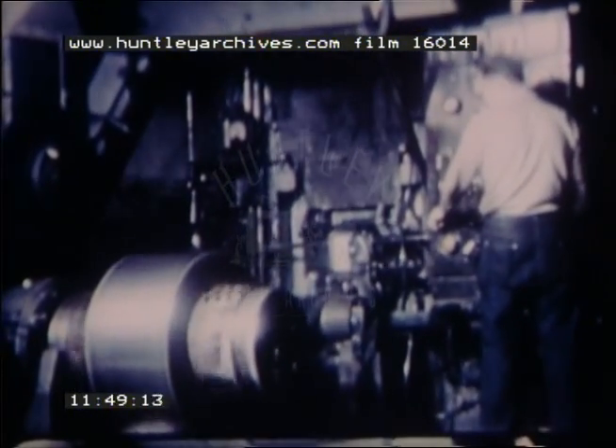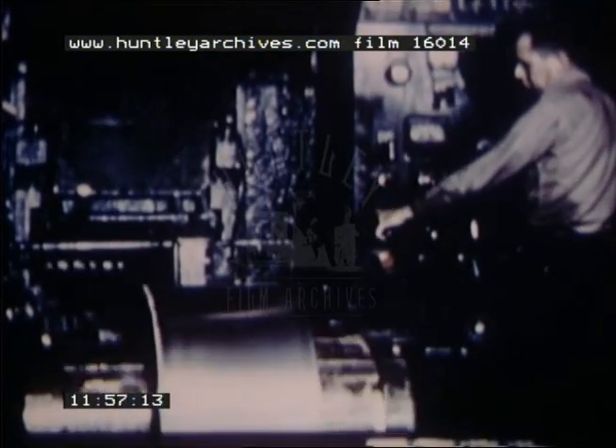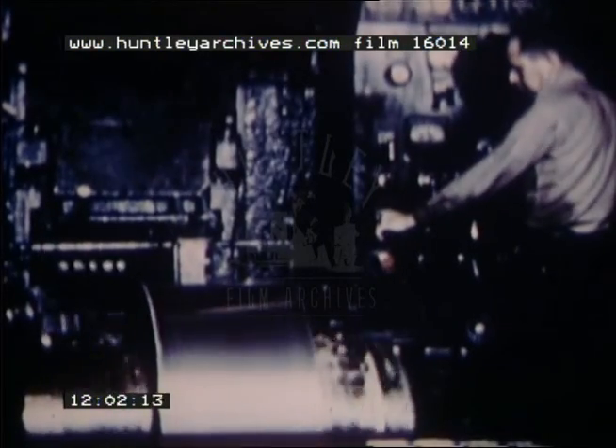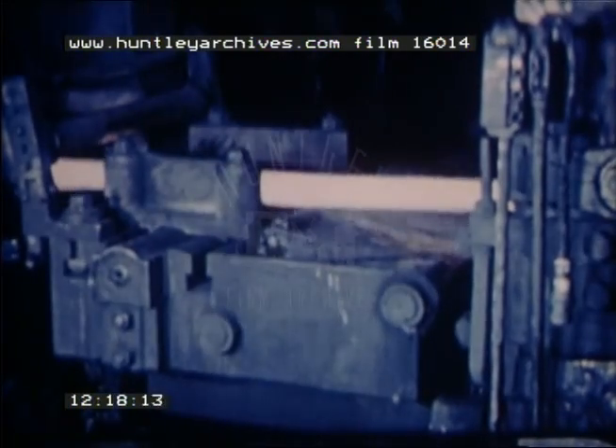Cold rolled steel, which is used by western manufacturers to make articles ranging from furniture to electric irons, from furnace registers to adding machines and toys, is rolled in this mill. Coils that have first been pickled to remove scale are reduced to gauge by rolling back and forth, giving the steel an extremely smooth surface. Certain kinds of pipe are made from an intermediate product known as skelp, which is rolled from slabs that pass through a series of 10 stands of rolls. As the skelp passes through this mill, it becomes thinner and longer, and each succeeding roll stand must turn faster than the one before to take up the slack. Strip for the cold rolled mill is also produced here.